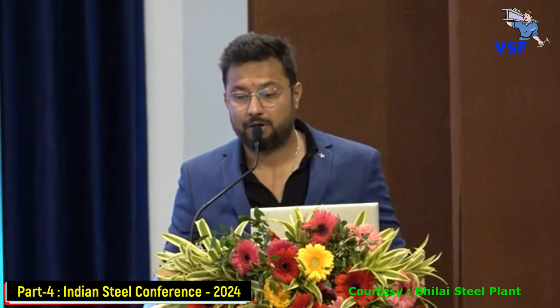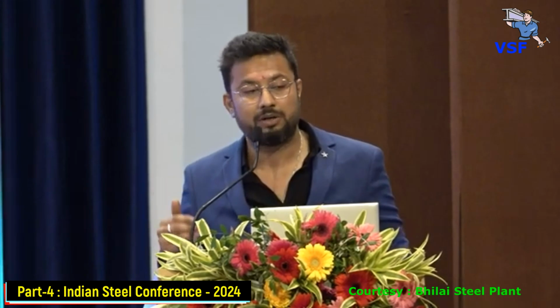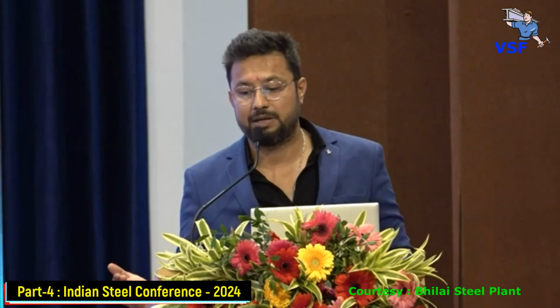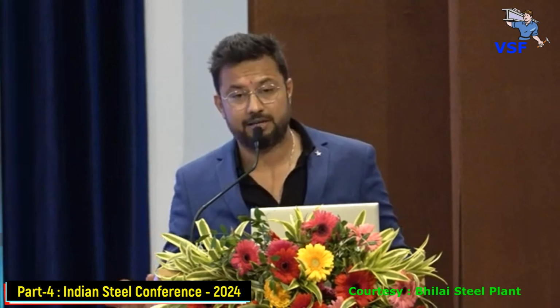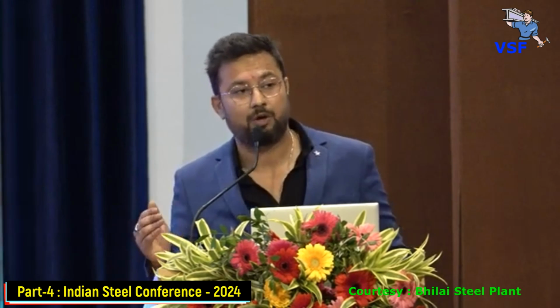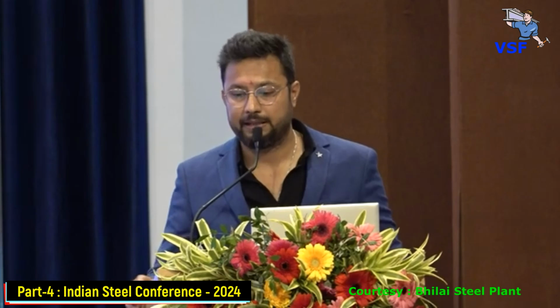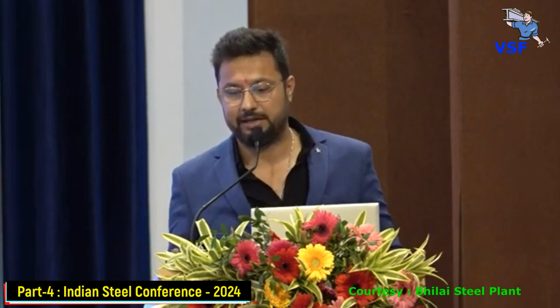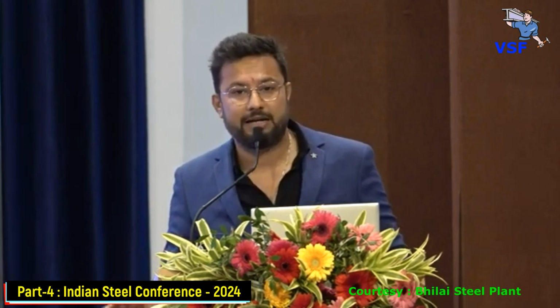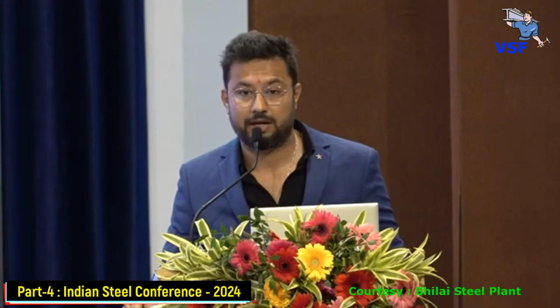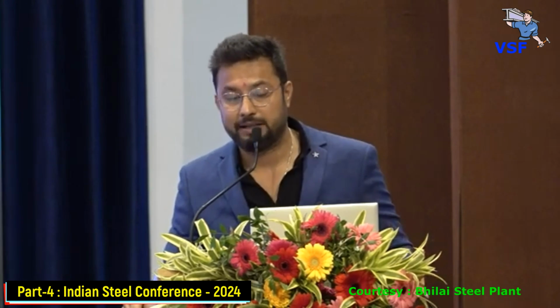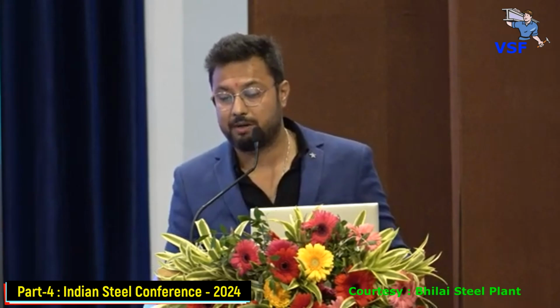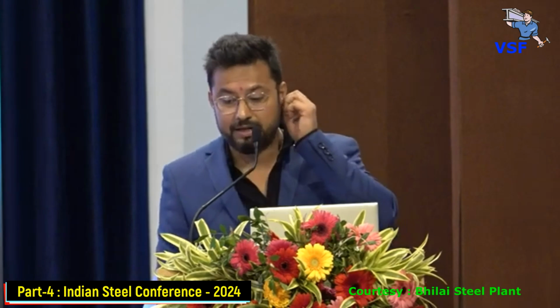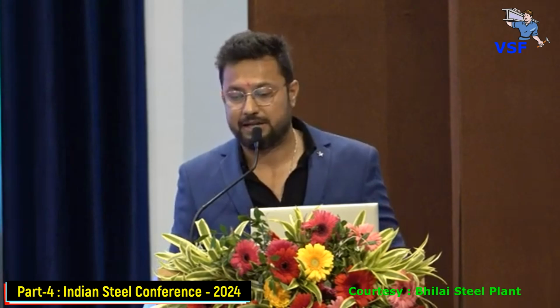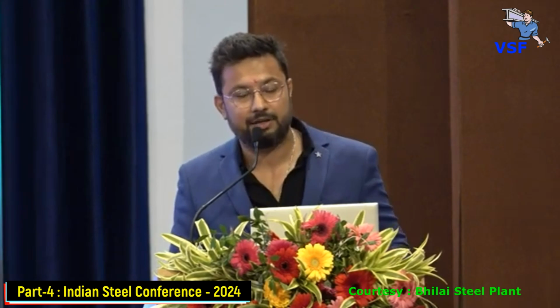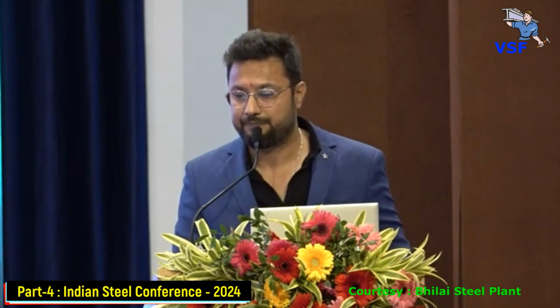Then, one important point is we are able to decrease the dependency on the alloying elements, where for 350 HD we are saving around 0.1% of chromium. Then again, there are process stability and consistency. We don't require any additional heating equipment for a head hardening system. Then, of course, we have reduced installed power, reduced maintenance, and a shorter commissioning time. This we will go into when we see our client testimonials.